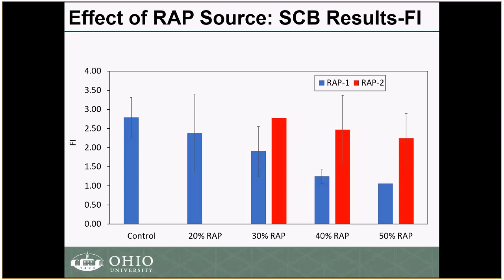So the effect of the RAP source was very important: whatever results you're getting for one RAP, you cannot really extrapolate to another RAP. That is very important for this study and for the local public agencies who would like to implement it, that you need to look at the RAP. And the results here show a significant difference in terms of the fatigue cracking resistance between RAP 1 and RAP 2, as indicated by the flexibility index.